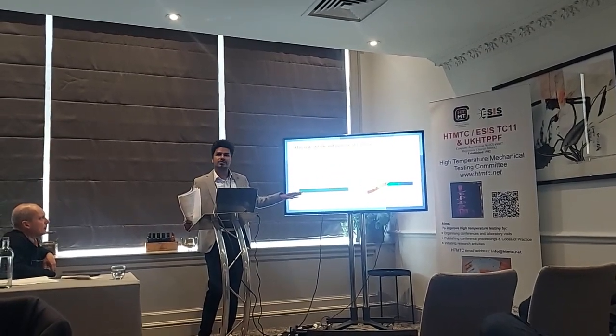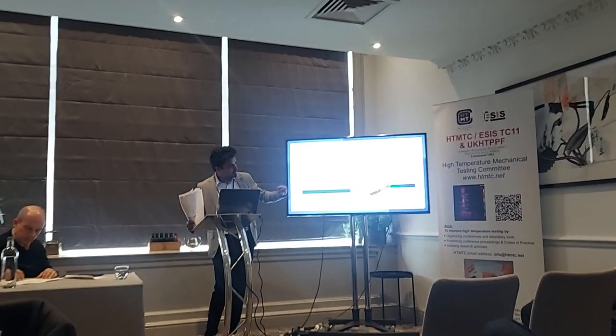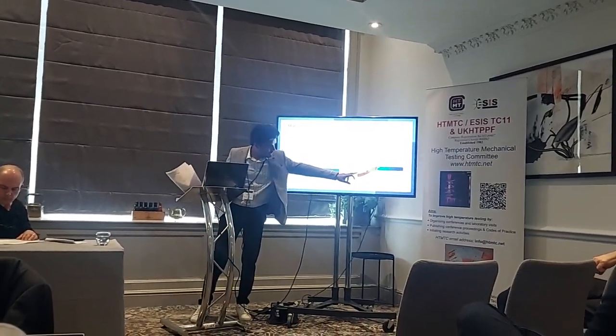Now we will talk about the numerical simulations and materials. This study involves previously tested models for two different materials, Incoloy 800H and Sanicro 25, with identical geometry and boundary conditions. The finite element software Abaqus is used to model and simulate the small-punch creep test. The axisymmetric model is shown, along with the simulation results indicating four different locations: upper node and lower node at the central location, and upper node and lower node at the maximum thinning location. The results of the SPCT — data versus time — have been compared with published experimental data to validate accuracy.